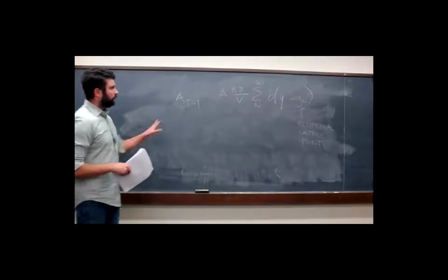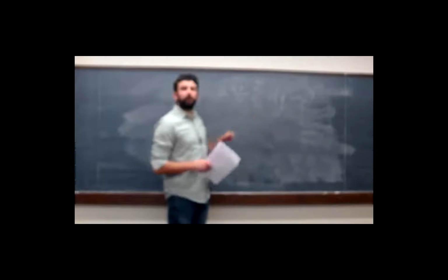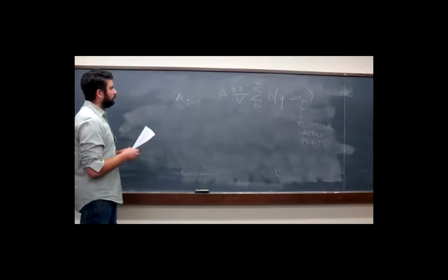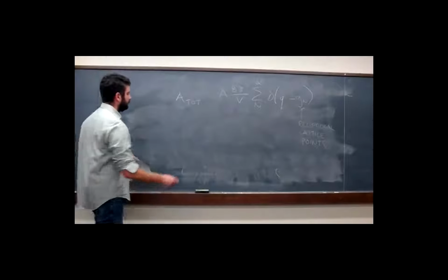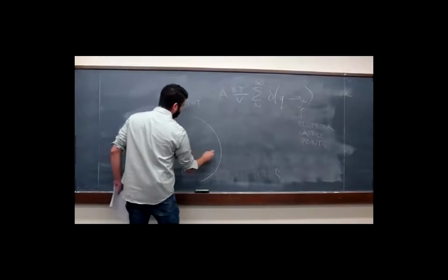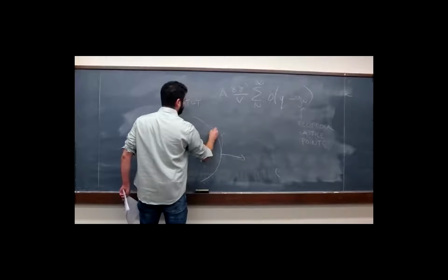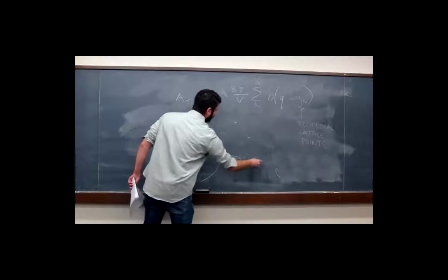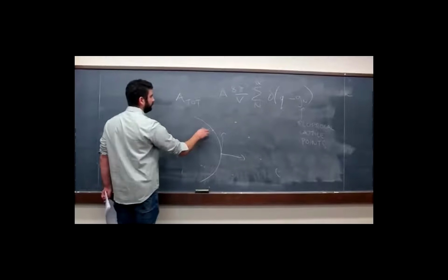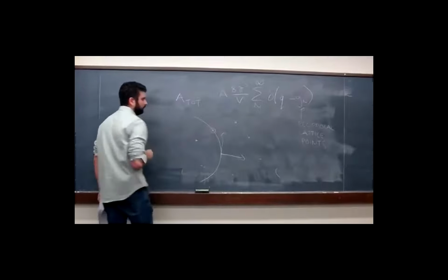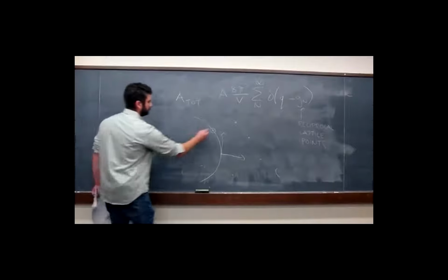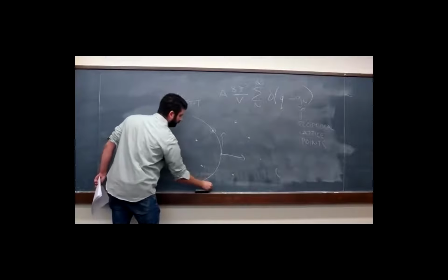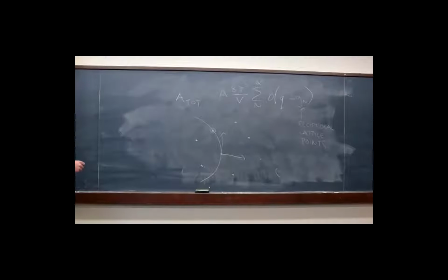So with this being the case, we can think about our Ewald sphere construction a little bit differently than we have been. Previously, we were just kind of sitting in reciprocal space, but what we're actually seeing during a diffraction experiment, where we've got a piece of Ewald sphere in different lattice points, reciprocal lattice points spaced out, is that what we're able to see is the Fourier transform of the charge density, which is in contact with Ewald's sphere. So what we're seeing is a little slice of the Fourier transform of the charge density at any given time.